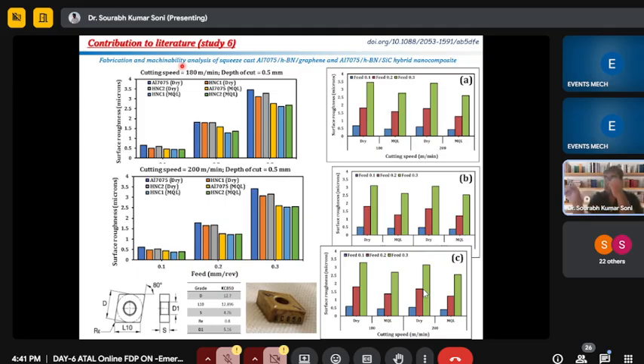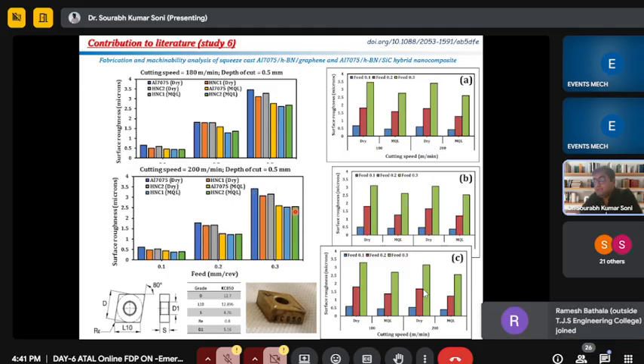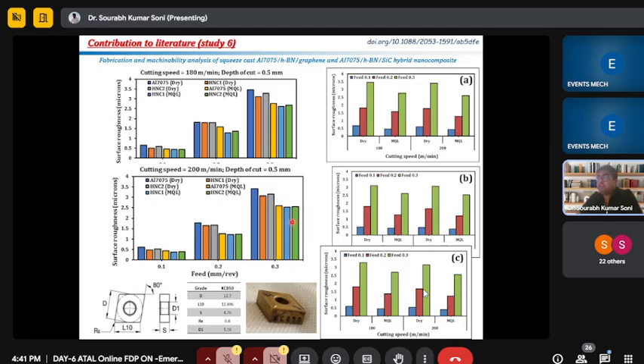For preparing this MQL, we have used the HBN nanoparticles also, so that we can improve the efficiency of the working fluid. Here we can see if we increase the feed rate, surface roughness is increasing. This one is the aluminium 7075 specimen. This is the hybrid composite specimen. In the hybrid composite specimen, we are observing less surface roughness.